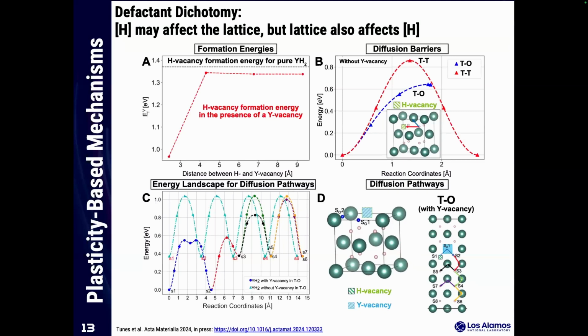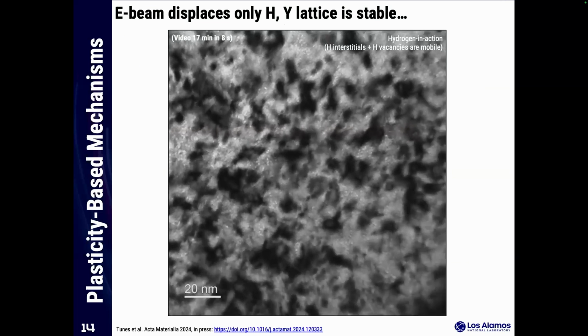Our major objective with this is, if a vacancy, if yttrium is displaced in this microreactor due to radiation, the hydrogen vacancy formation energy is reduced. So you have a total vacancy population of hydrogen and yttrium enhanced. So the radiation damage increases in these hydrides, causing disturbance in this hydrogen lattice. We want the hydrogen to be there.